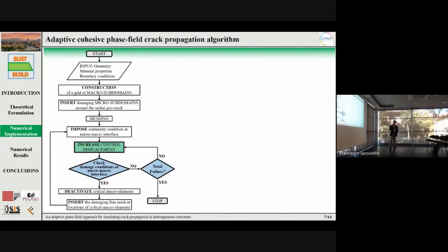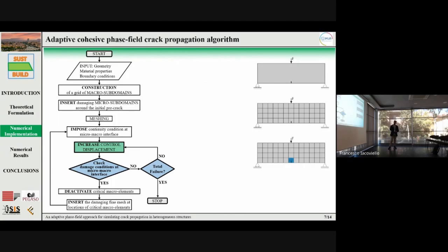The crack propagation process is managed by an automatic algorithm. The analysis starts by defining geometry, material properties, and boundary conditions. The computational domain is divided into a macro subdomain, and within a zone of interest, micro subdomains are inserted. At the interface between micro and macro subdomains, continuity conditions are imposed to ensure that the transition between the two different meshes does not introduce artificial discontinuity on displacement fields or stress. At this point, the analysis starts by increasing the control displacement.